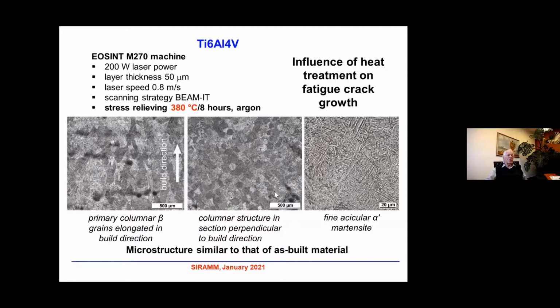Let me say some words about microstructure. I told you that the as-built specimen has to be somehow treated by temperature treatment, heat treatment. This material was prepared on an EOSINT M270 machine. The laser power was nearly 200 watts and the layer thickness was 50 microns. The laser speed was 0.8 meter per second. And again, the scanning strategy was called BEAM-IT. The stress relieving was done at 380 centigrade for 8 hours in argon. Our aim was to study the influence of heat treatment on fatigue crack growth.